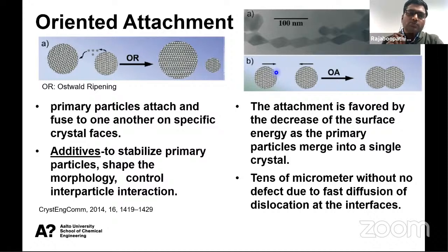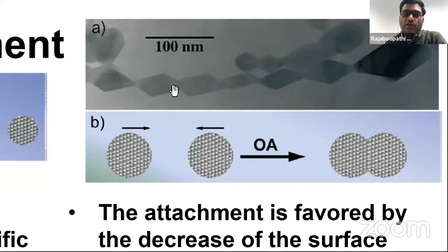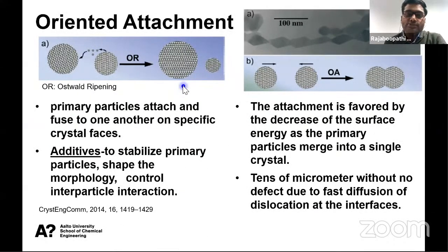Oriented attachment is similar to Ostwald ripening, but here, see, these are two particles. The two particles attach together to produce an oriented structure. We can say it is oriented attachment. Here there is no lattice mismatch in the oriented attachment. This is the only difference. In the oriented attachment, there is no lattice mismatch between the two particles. So this is the difference between oriented attachment and Ostwald ripening, though the process looks the same.